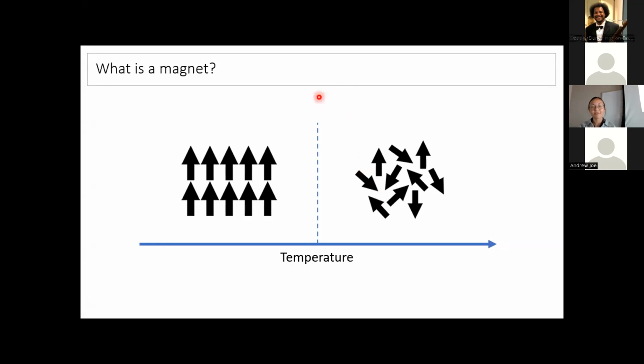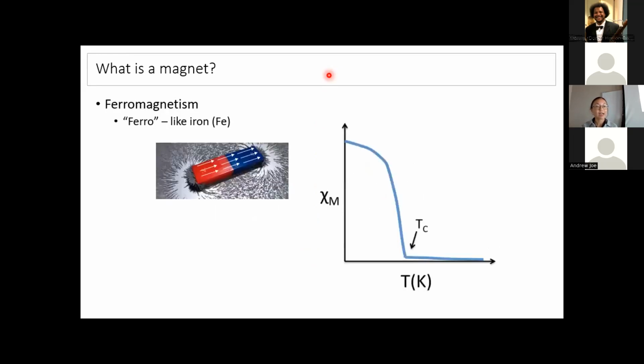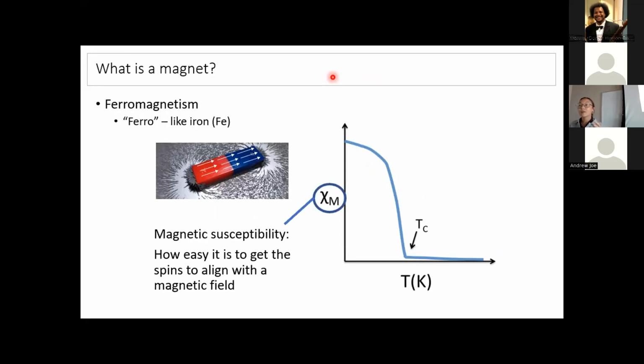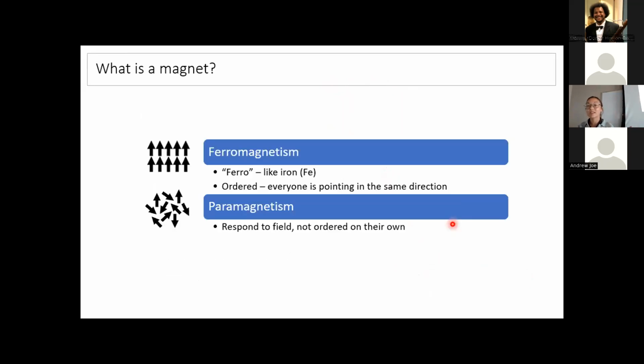Okay, so this is a phase transition between two different kinds of magnetism. If we want to actually look at what that looks like, instead of just saying this sticks to the fridge, now it doesn't, one thing that we can measure is what's called the magnetic susceptibility. This is basically how easy it is to get these spins to align with a magnetic field. Another way to think of it, although it's slightly different, is that you're adding up all of these spins. They're all pointing in the same direction, so they add up to each other instead of canceling out. And below a certain temperature, this quantity jumps up, and above a certain temperature, it's more or less zero. So down here, we have ferromagnetism. Up here, we have something else. And that something else is what's called paramagnetism.